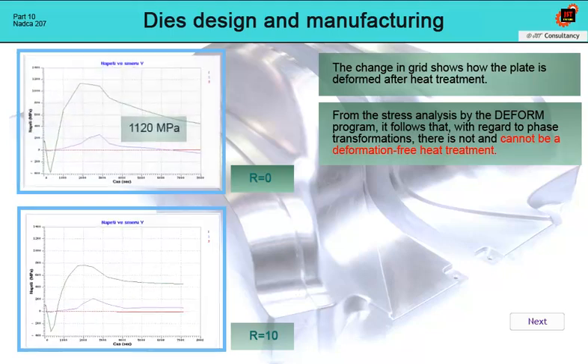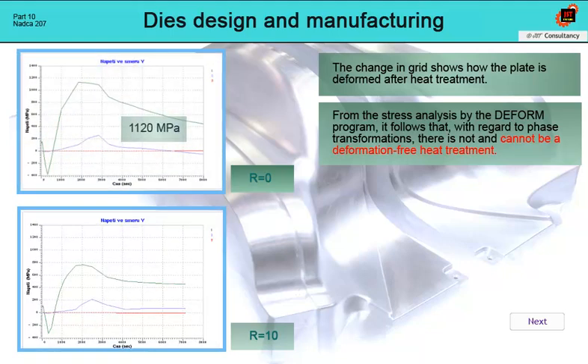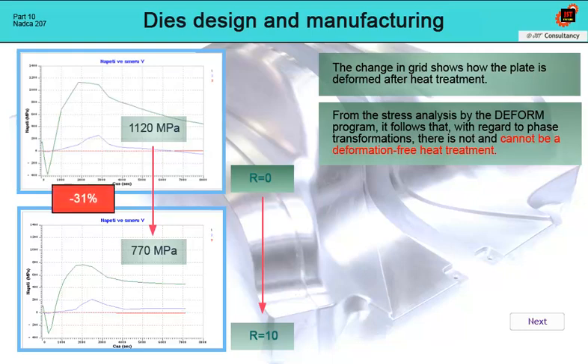In the case of a notch with a radius of 0, a maximum tensile stress of 1,120 megapascals was identified. In the case of a notch with a radius of R10, then 770 megapascals. So the stress dropped by only 31%. So what does this mean? If we want to prioritize small deformations over the structure, and we want to cool slowly during quenching, we will still not achieve a deformation-free state, precisely with regard to the above.